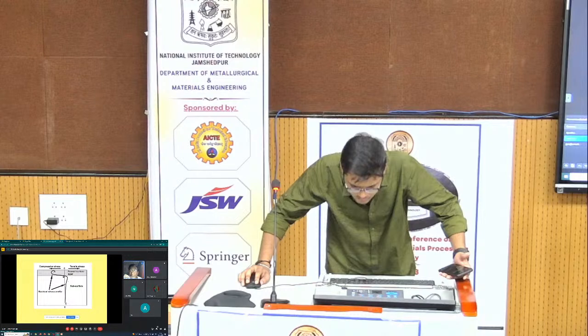Why? Because all my fatigue cracks, I repeat, originate from the surface. So therefore, the propagation and also the creation of these discontinuities on the surface, their chance will go down if I have a compressive residual stress. This is the important part. And today, it is not only the steel ball or silicon carbide, we can do laser peening with stand-off distance. If I have 3 feet, 4 feet stand-off distance, even then with laser ablation, we can do what is called laser peening.